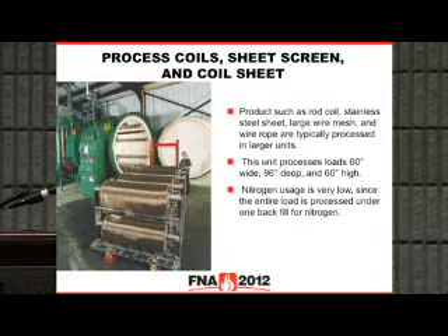This particular customer was the one that actually had a very short payback strictly on the vast amount of nitrogen that they were going to be using. This wire mesh has really slow heating rates and slow cooling rates. And so they had a 24-hour cycle that they would have been running nitrogen the entire time and at some pretty high flow rates. So in this particular case, they would do one charge. And you can also carry the one charge into double temper and triple temper for tool steels. And that is additional savings.